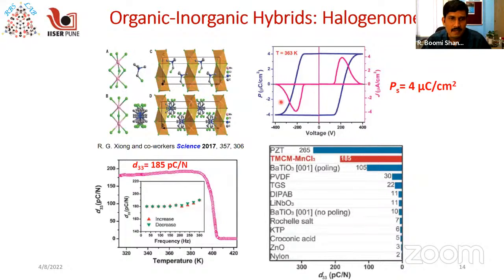of a material. And this material also shows an additional piezoelectric property. The d33 value, which is a piezoelectric coefficient, is close to barium titanate and lead zirconate titanate, which is very rare for small molecule based systems. As a result, these studies prominently indicate the potential of organic-inorganic hybrids and organic molecules for technological applications.